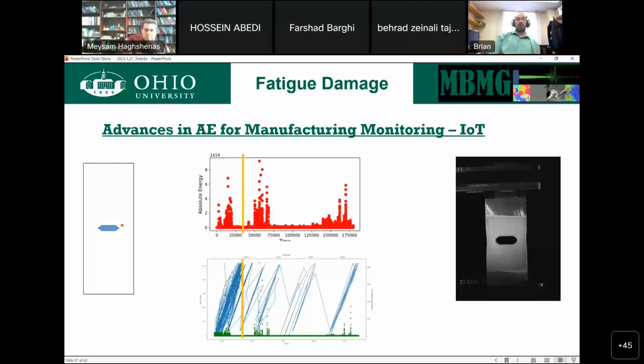And we can do the AE without having to take images, which means less storage space, which is a huge advantage. Now, the downside to anything to do with sound traveling in a material: there's a crack here, which means if I place my sensor next to the notch or above it, I will have different results, different waves. The trends can still be there, but what the wave looks like is different, and that makes it a little bit more challenging to make this methodology material and geometry agnostic.